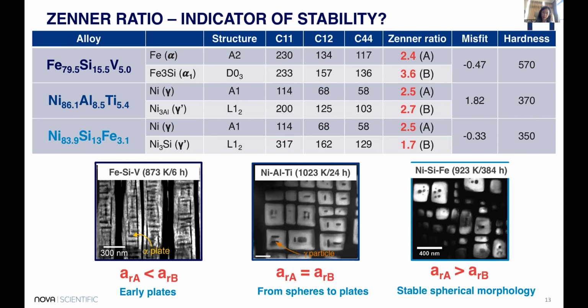We categorize the morphological evolution of hierarchical particles in three different ways according to these three different alloys. First, early formation of plates. Second, morphological transformation from spheres to plates. Third, stable spherical morphology. Comparing that to the Zener ratio of each phase, which is the ratio of elastic anisotropy, we conclude certain pairings of Zener ratio will favor a particular morphological evolution of hierarchical particles.